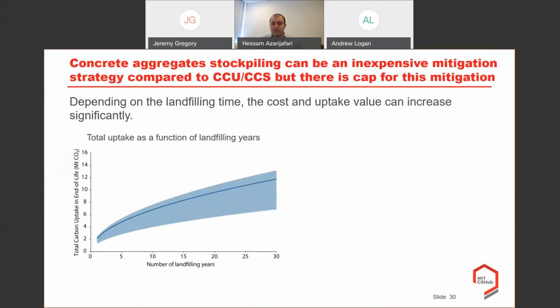Let's go further and talk about the possibility of increasing this carbon uptake at the end of life. The strategy is to leave these stockpiles for a longer period of time, and you can see that there is a non-linearity in the total carbon uptake as we go forward in time. And it's important to note that we don't necessarily need to landfill this concrete for more than 30 years or so, because the uptake will definitely become smaller as a function of time when we are stockpiling the concrete at the end of life from 2 years up to, for example, 35 years, again following the fixed diffusion law.